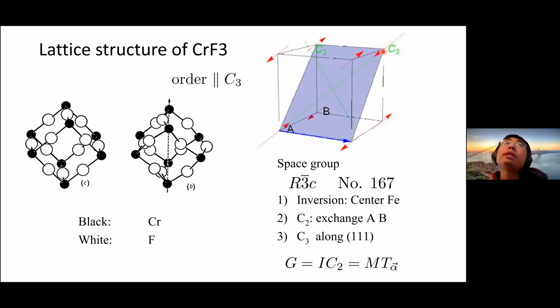In addition to these three symmetries, there is also another symmetry, which is a glide reflection plane. This glide plane is shown by this purple plane here. It includes a mirror reflection with respect to this plane, combined with a translation, and this translation is only half of the translation between the A and B sublattices.